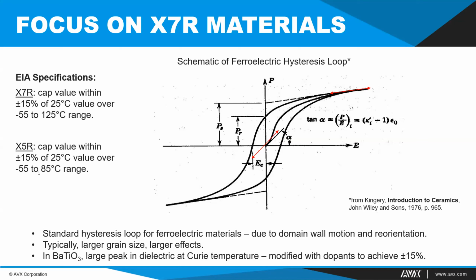X5R capacitors exhibit some of the similar properties, but their range is limited to 85 degrees C. And many devices that are X7R meet this temperature range, which actually implies a reliability of the device too, up to 125 versus 85. But many X7Rs will actually meet the 125 degrees C reliability specification as well. So the idea is to keep in mind that these devices have taken the bulk capacitance market in a large case, and so that's why they're significant. And they are based on barium titanate.